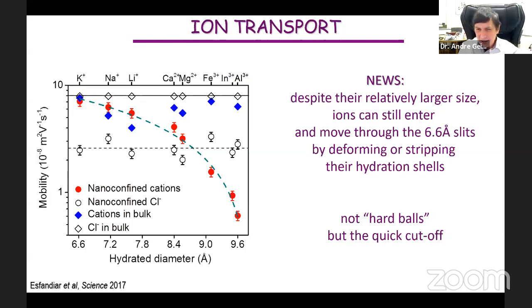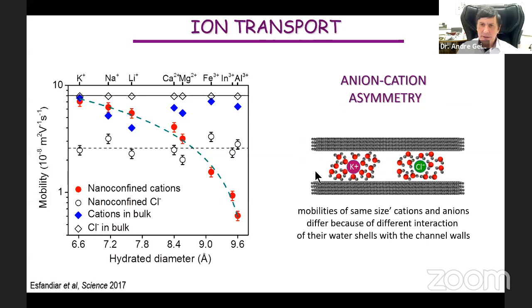And essentially this is what you expect from the model I just described, because the size of the hydration shell depends on the charge. The smaller the charge, the smaller the hydration shell. But as you see, charge is not the only dominant factor; even for the same charge, you already start seeing that the size of the hydration shell also matters.